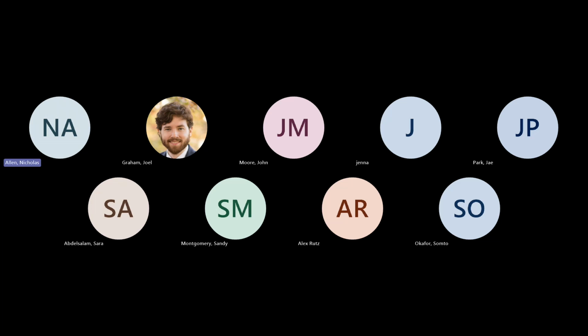So I haven't looked at packing multiple millimeter sized gels. I would imagine that the properties would probably change. With the granular hydrogel, the background behind the dynamic mechanical properties is that at the microparticle junctions, they are primarily dominated by frictional forces. And because the material is greater than 10 microns in diameter, but still on the micrometer scale, gravitational forces completely overtake thermal forces. So you get very specific mechanical interactions that lead to those dynamic mechanical properties. At the millimeter scale, I would guess that they would probably not operate in the same manner.